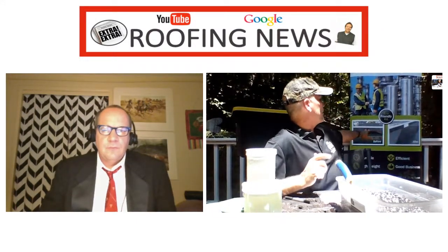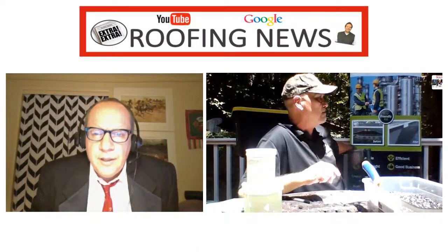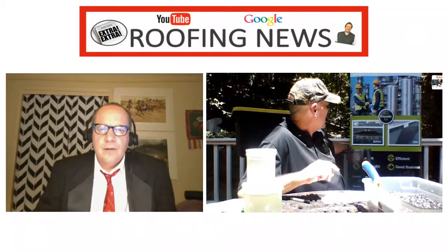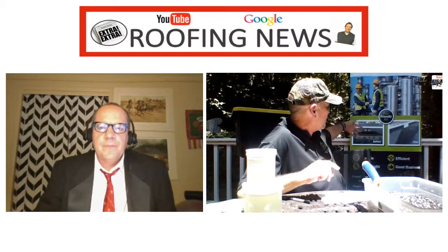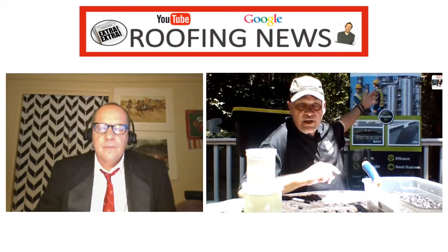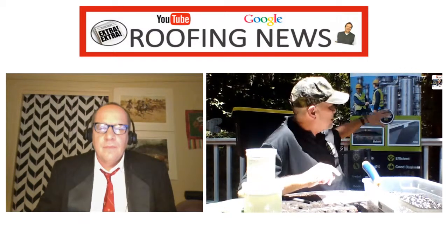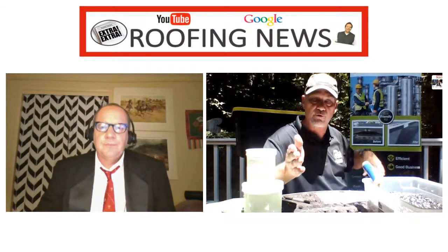This is a good example here. There's a nice EPDM roof. I don't know if you can see that or not, but they have basically old scuppers. The water settles right in front of the drain scupper, and that's very bad for the roof. It gets worse and worse over the years. So we cleared around there, cleaned it, put the green slope down, and then we top coated it with a white urethane that we wanted to put on the rest of the roof. So we did the repair and top coated it with what we were wanting to price for the rest of the roof area.